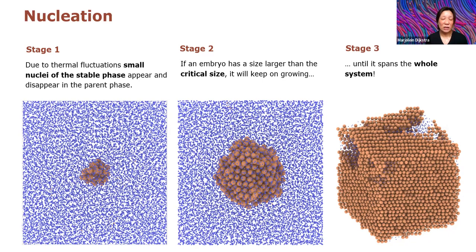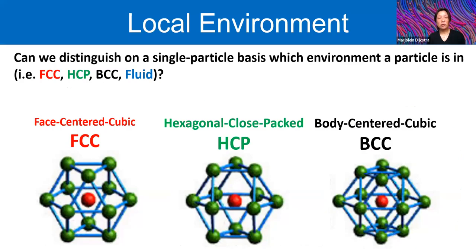And so here I already cheated a little bit because I plotted the solid-like particles already in brown and with their actual size, and the fluid-like particles I plotted 10 times smaller and in blue. So I really needed here, in order to do that, a good order parameter that can tell you on a single particle level whether a particle has a fluid-like environment or whether a particle has a solid-like environment. And this is actually very tricky to do, because if you really want to do that on a single particle basis and you plot, for instance, the typical particle in a face-centered cubic or a hexagonal close-packed or a body-centered cubic crystal phase, you immediately see that the environments are very similar to each other.